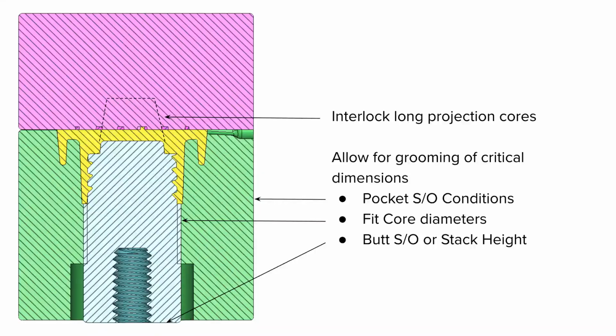Likewise, where the core fits inside of the B-side cavity block, we left material there and trued the outside of the core up, and we ran a reamer down through the hole. So we're fitting our core diameters, and then we're fitting our butt shutoffs and our stack heights so that we are maintaining the best quality of molded part as we can. Next slide.